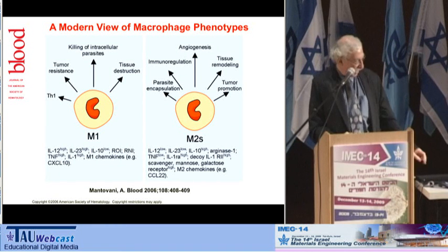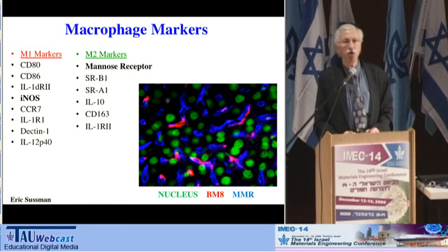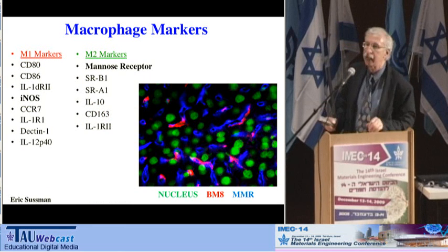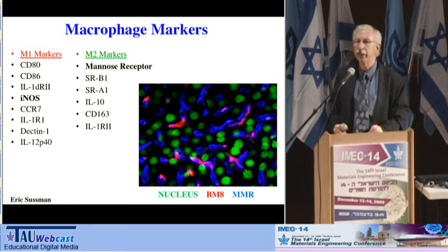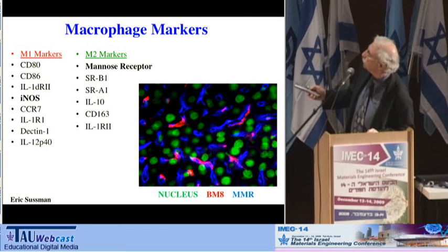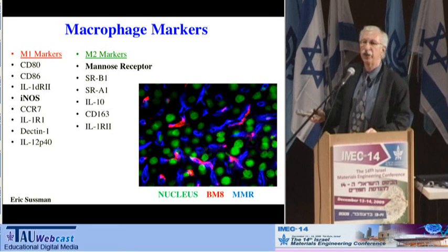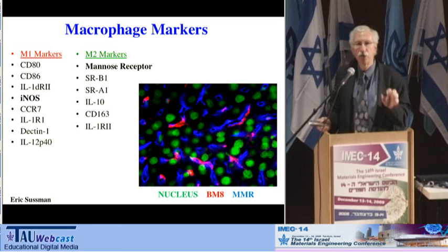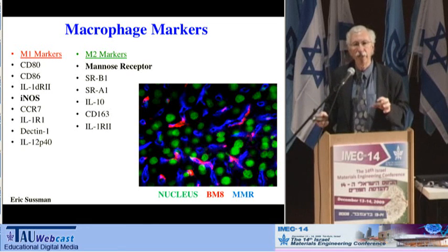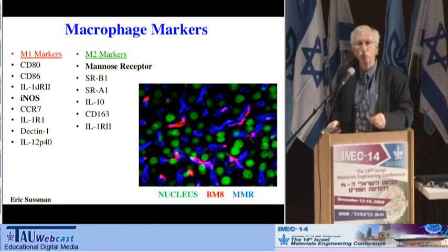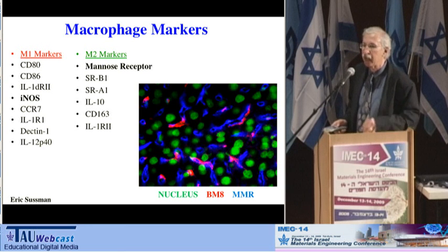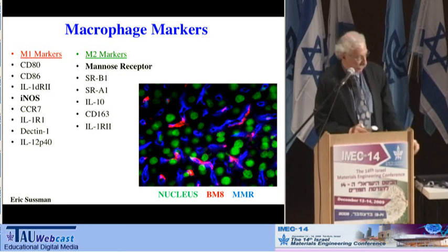So are we getting M2 macrophages? Well, the initial results, actually the data isn't down here, but the results are in, and this just shows our ability to stain the macrophages in the different phenotypes. But the results are in, and it shows that, in fact, within these sphere-templated materials, there's an enrichment of this M2 phenotype that leads to healing and reconstruction.